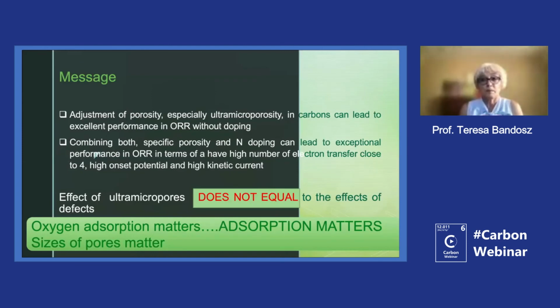So what is my message at the end? We think that adjustment of the porosity and those small pores is important and can help with ORR efficiently. And if we combine the N and S, for instance, or boron doping in larger pores and the porosity, we can get a really good catalyst. And we think that the effect of micropores does not equal the effects of defects. And so oxygen adsorption matters.